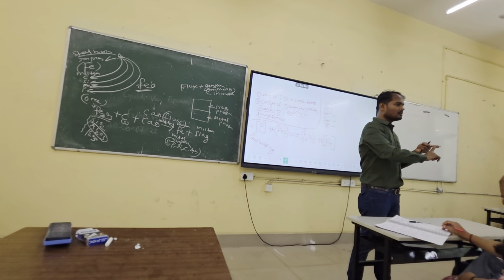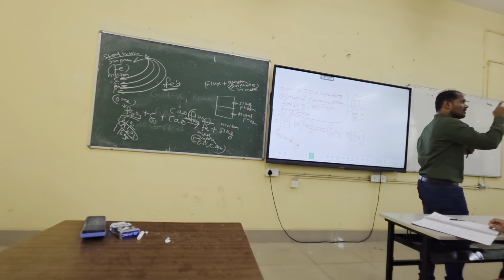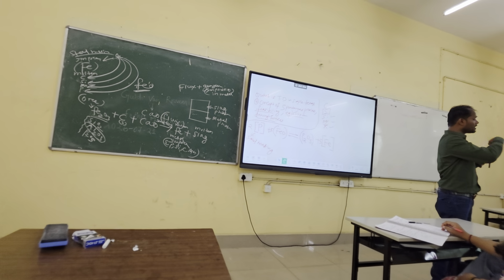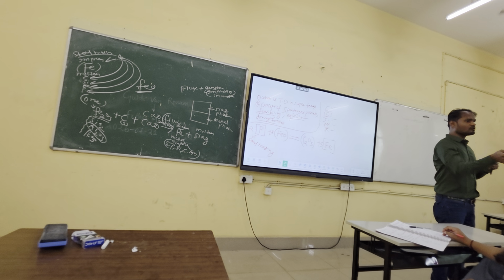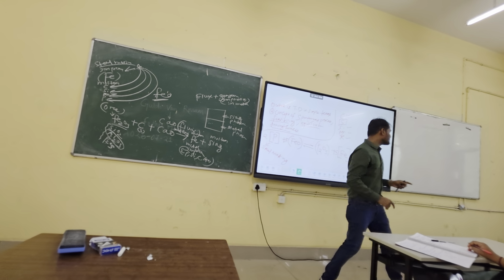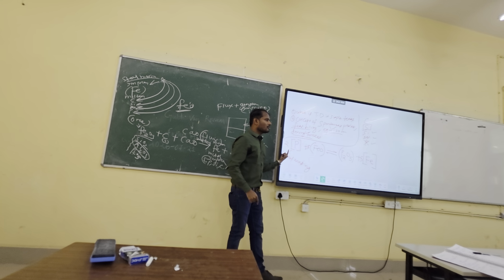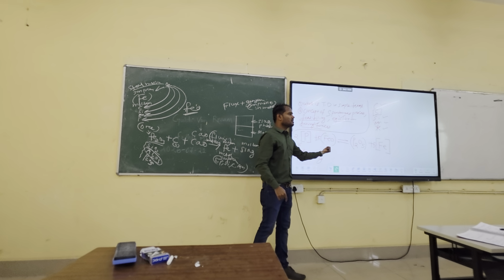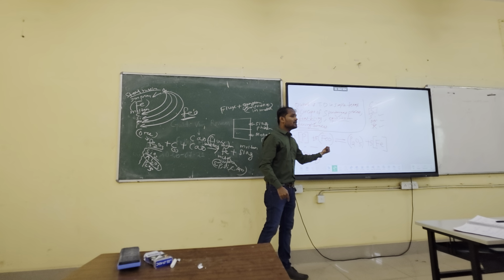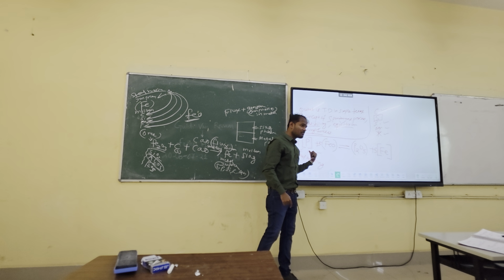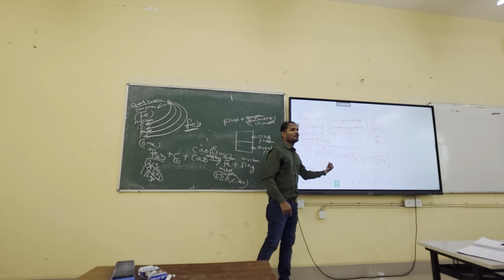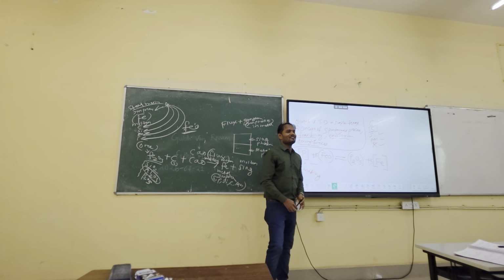So two things are happening. One is direct reaction of oxygen with the phosphorus, and another reaction is the FeO which is already formed and moved to the slag phase. That also reacts with the phosphorus. And why does this reaction happen? Can you tell me? Already I told you why this reaction happens. That means because P2O5 is a more stable oxide compared to FeO. Or in other way I can say phosphorus has more reactivity towards oxygen compared to iron.